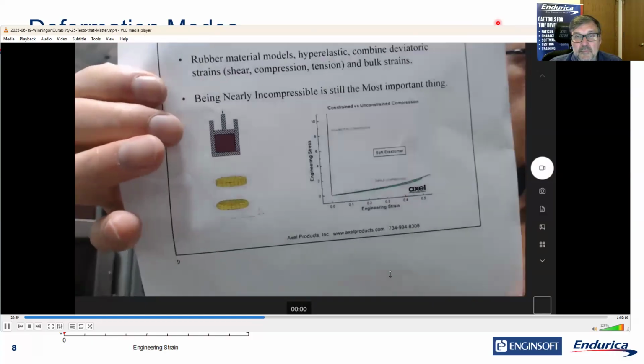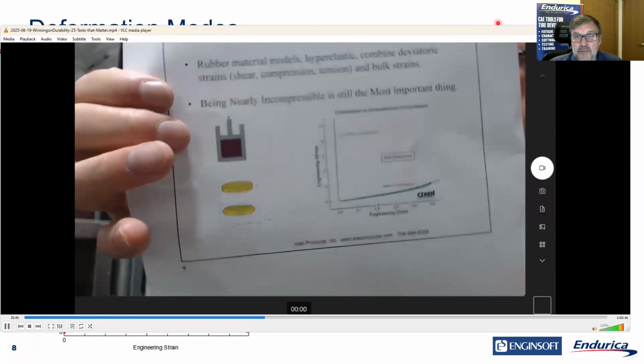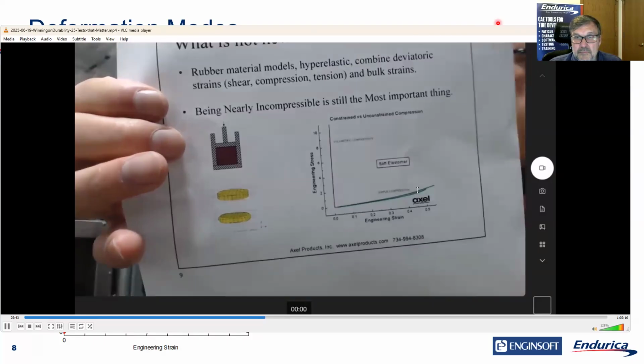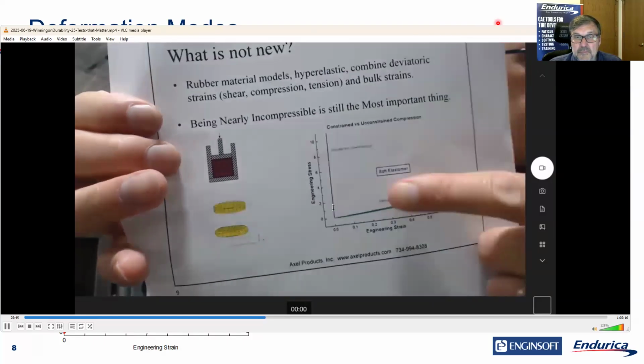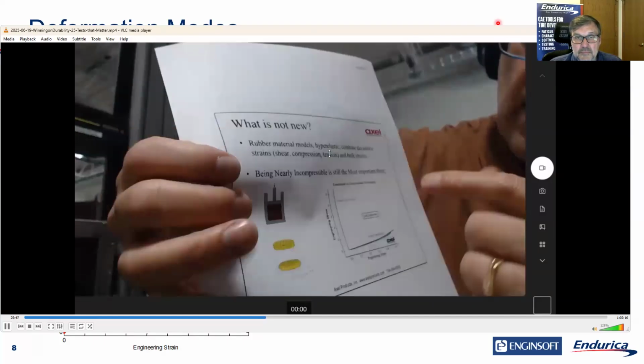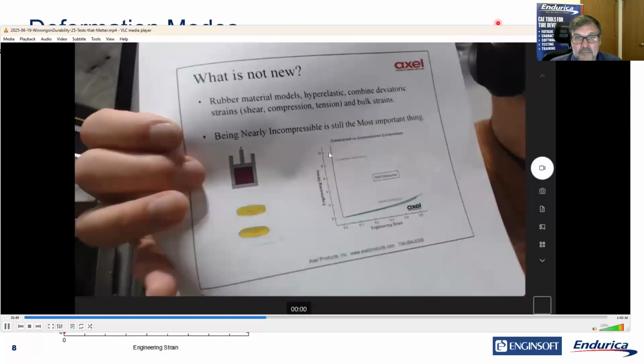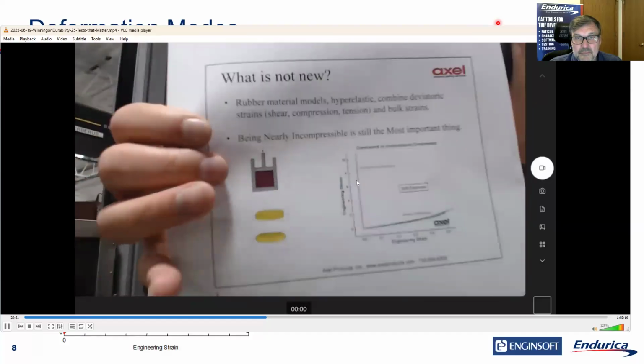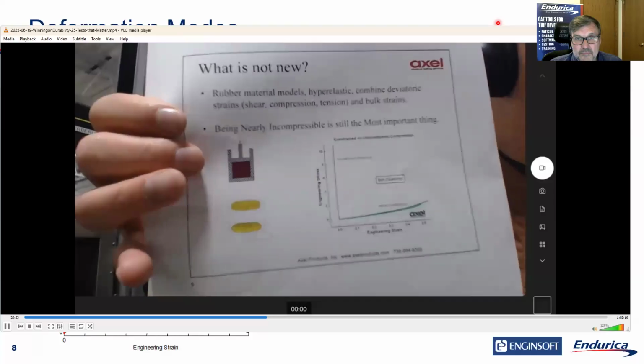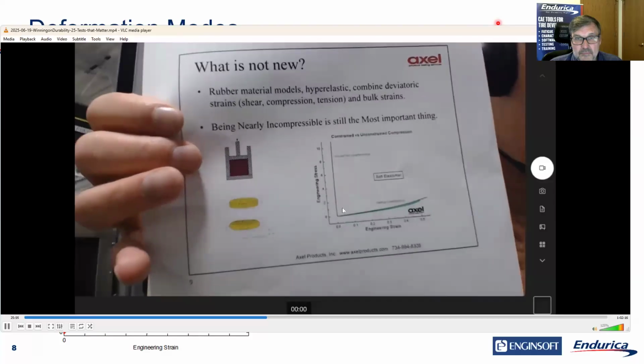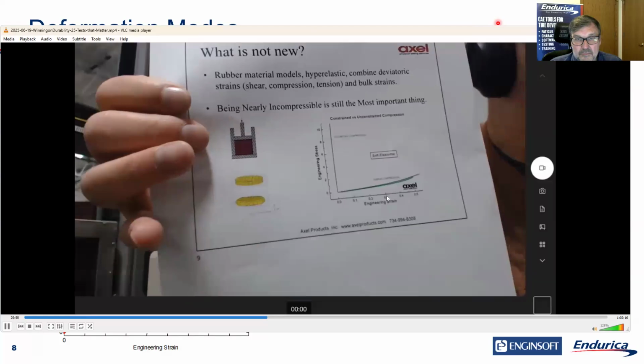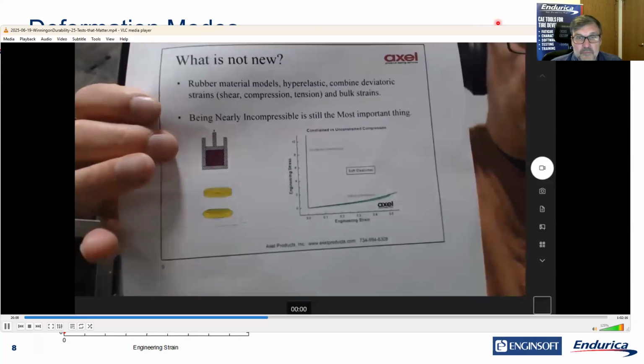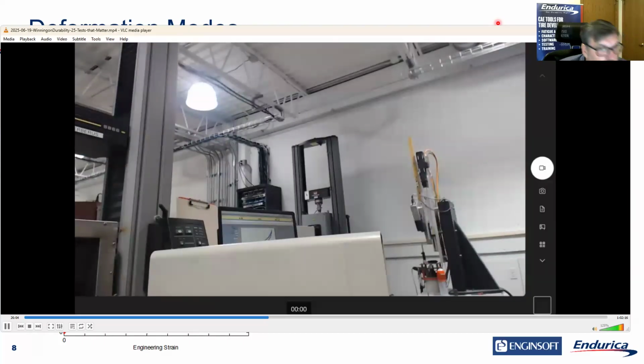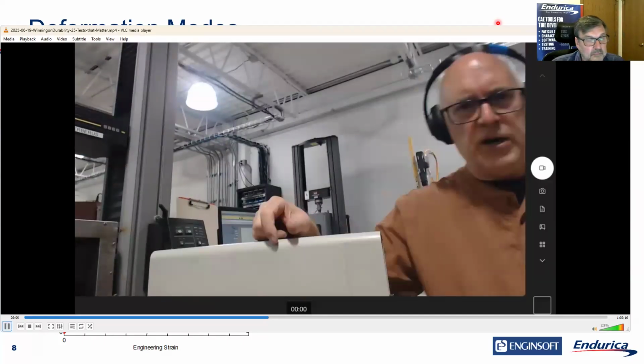On the right-hand side of your screen, the bottom curve is a compression test. The top curve right here is volumetric compression. That's the stiffness difference between bulk stiffness and compression or basic shearing. It's massive. So when we talk about rubbers not wanting to change their volume, we're not kidding. It doesn't want to change its volume. It's enormously stiff when constrained.